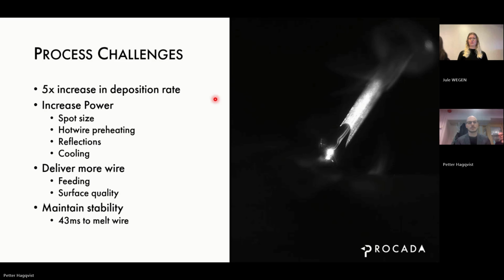We also had to increase the power in terms of hot wire preheating. So instead of first converting electrical power into light and then having the light heat up the material, we're just having the electrical power going straight into the metal, heating it up, which is very efficient, but it's also a bit risky, because if we introduce too much electrical current, we will get an arcing event. And these arcs will create small explosions, which could agitate the melt pool, and thus, as we learned previously, lead to pores.